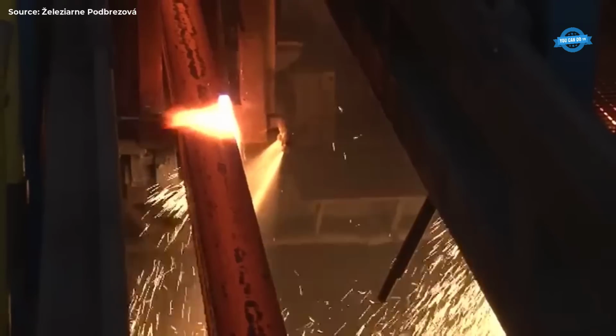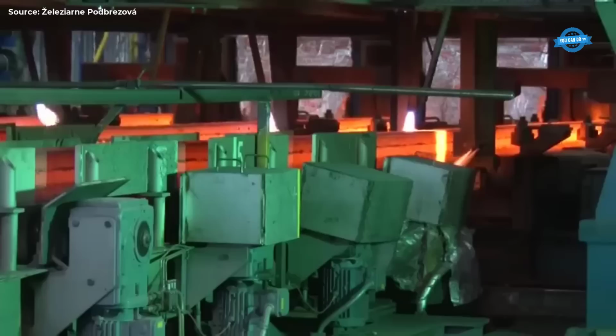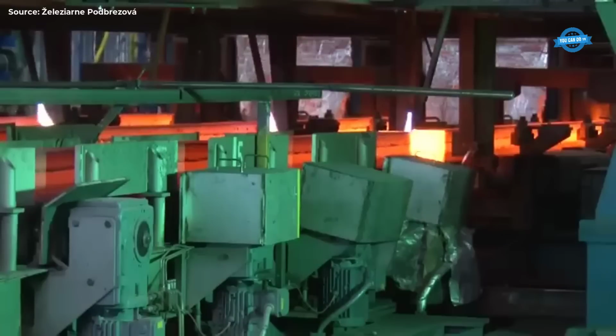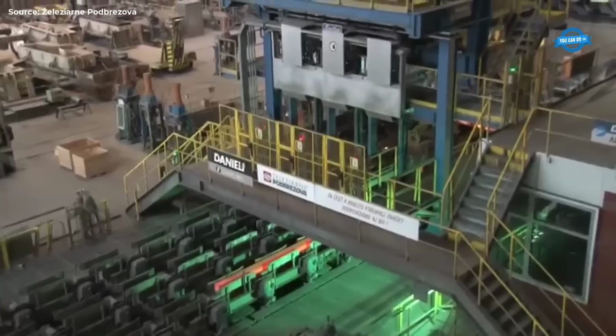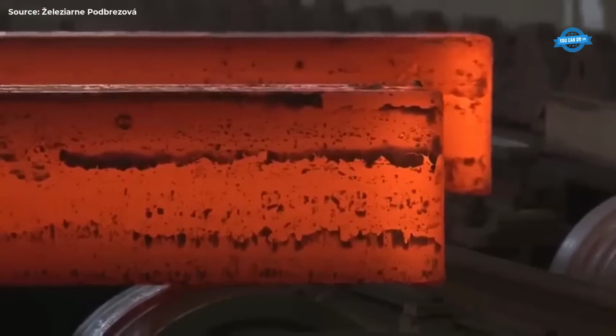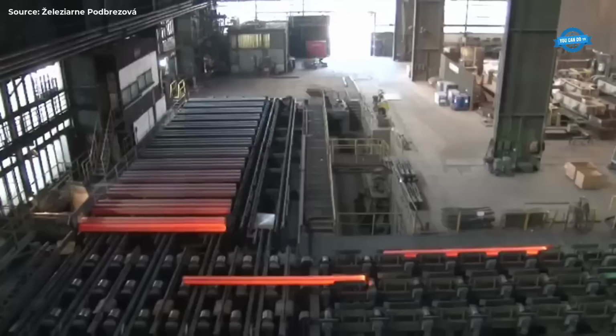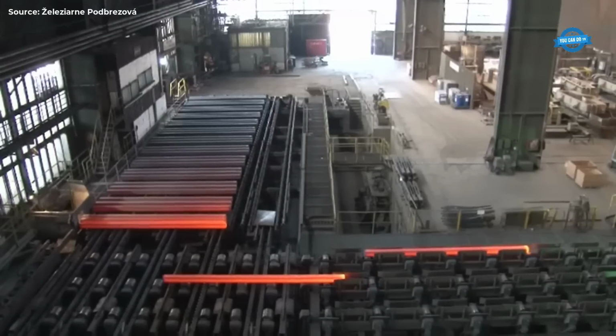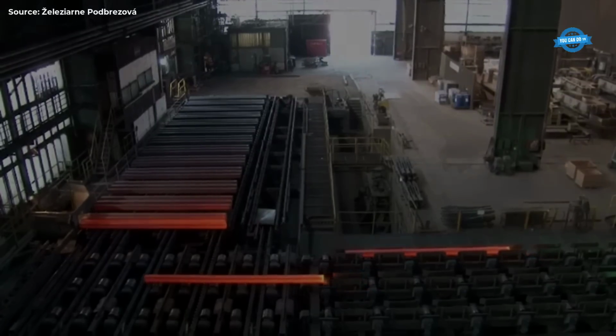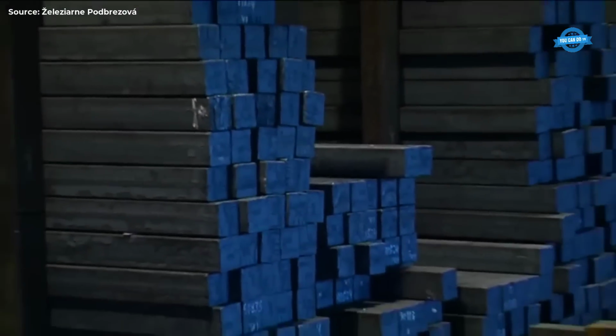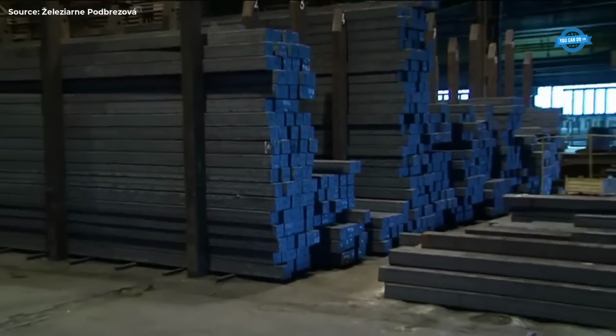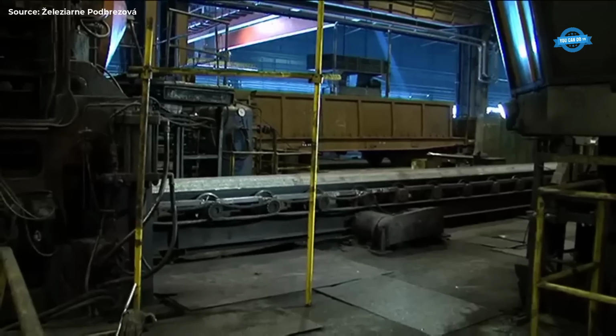The molten steel is continuously cast into blooms with square or circular cross-sections. After cutting, marking, and cooling, the final quality control is performed before the blooms are transferred to the rolling mill. With an annual production capacity of 370,000 tons, if the steel blooms were placed end to end, they could form a continuous line stretching from Podbrezova to Brussels.